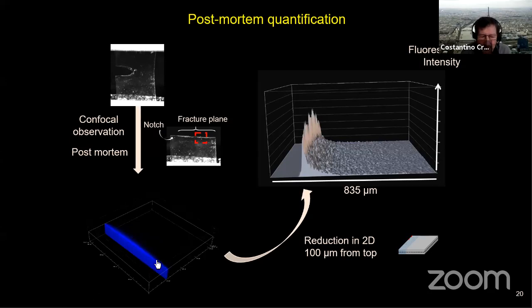Now here you cannot see the length, but in this particular case, this is a sample broken relatively close to its glass transition temperature. This is about 800 micrometers, so a much larger scale than the molecular size. And we detect quite a bit of bond breakage if we look at the distance here from the surface. Now, this type of data is of course in the direction of propagation. So the crack propagates into my screen in this case. So we can average it and we can get an average profile by averaging the data, again, for different conditions.